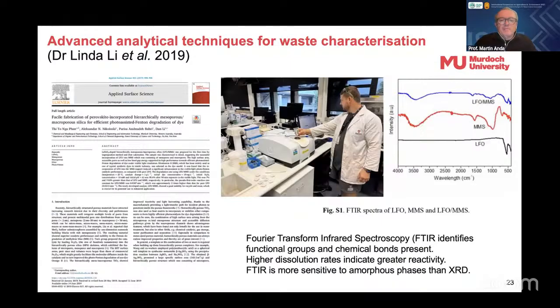Now, what we're starting to move into now at Murdoch University, and you can see here, Greg, in the photograph, is the use of other test methods as well, like this machine you can see in the photograph, the Fourier transform infrared spectroscopy. And this is looking at the functional groups and the chemical bonds present in the geopolymer. And from this FTIR scanning, we can see the dissolution rates that indicate the level of reactivity. And what we've learned is that the FTIR is more sensitive to the amorphous phases than the XRD.